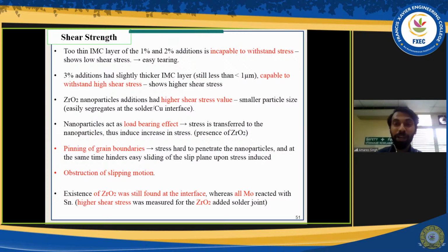So when you have lesser than 1 micrometer IMC layer, it's still capable to withstand high shear stress. But then looking at the 2% molybdenum, it has a very low shear strength because although it is less than 1 micrometer, it's very, very thin. So perhaps it did not help in terms of shearing resistance. At the same time, a proof of hypothesis was there was no presence of molybdenum solid nanoparticles. As discrete particles, they were not there. They were actually in terms of a compound. But in zirconia, even though it reacts with tin and also copper, there was presence of solid or discrete zirconia. That is why we can see the shear strength of the zirconia in all 3% of addition was way, way higher than the molybdenum additions.